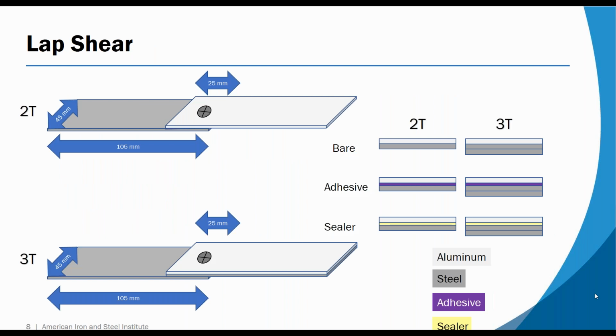For phase 2, we concentrated on the lap shear coupons because they were most suitable for the cyclic fatigue testing that we went through. As you can see, we used a 45 by 105 coupon for these.